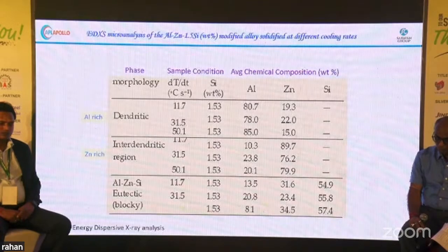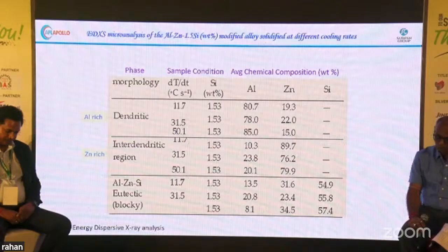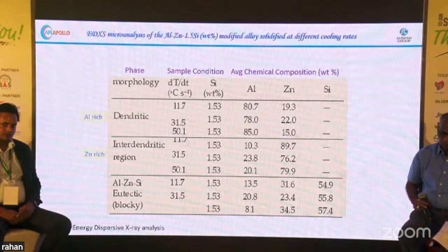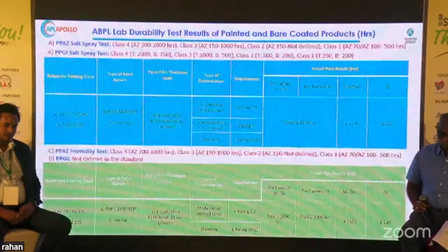Now this is the aluminum-rich phase, the zinc-rich phase, and the aluminum-zinc-silicon eutectic, which is blocky. What is in the aluminum-rich phase? Almost 80% aluminum and 20% zinc. In the zinc-rich phase, almost 80% is zinc, and something around 10 to 20% is aluminum. In the aluminum-zinc-silicon eutectic, 55% is silicon, and the rest is aluminum and zinc.